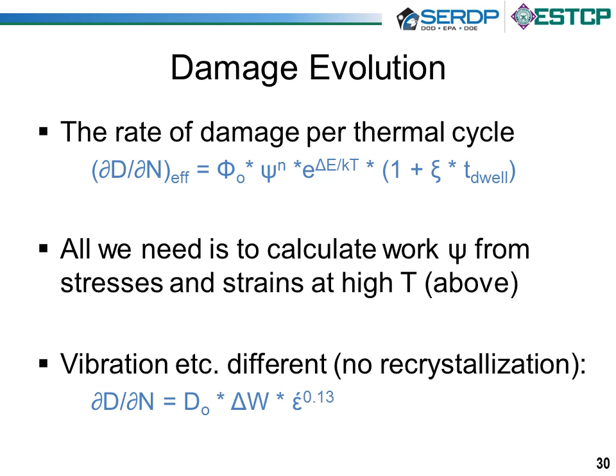And based on that, again, we can provide you with what we need for modeling, that is a rate of damage per thermal cycle that expresses it in terms of parameters that can, again, be measured or predicted or calculated. The temperature, and specifically maximum temperature in your cycle, the time that you're at that temperature, constants that we're providing you with, and then the work done during the high temperature dwell, which I said can be calculated because we can calculate stresses and strains and so on. So that is the entire constitutive relations for anybody who wants to predict life in thermocycling.